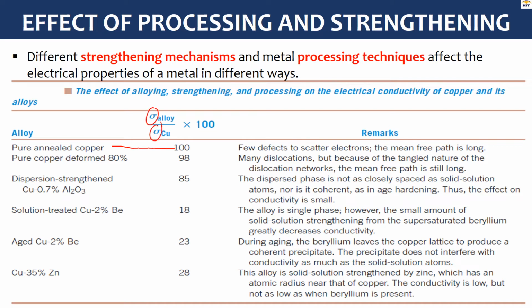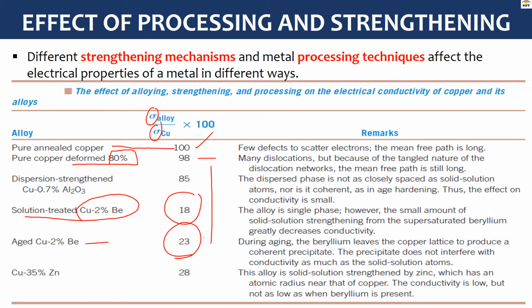your conductivity here of an alloy over copper times 100. So in this case, it is actually 100. Okay, 100, maybe 100%, in this ratio times 100. Okay, then when your copper is deformed 80%, there is a reduction in this ratio. When you, for example, age copper with 2% beryllium, there's a drastic reduction in the ratio to around 23. And in this case, the least one is the solution treated copper with 2% beryllium, which gives us a ratio of around 18. So we can see a decrease in this ratio when we do some strengthening mechanisms of our metal. Okay.